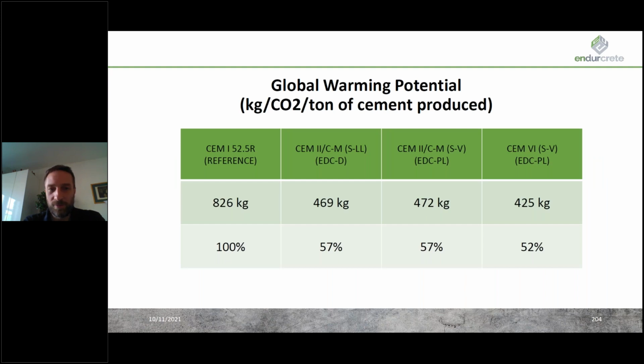So if we compare the global warming potential measured in kilograms of carbon dioxide, which is the most important parameter in this analysis, of the reference cement with the alternative EnDurCrete cements, we can see that we have achieved a very significant reduction. And maybe you remember that in the beginning Arno was presenting that the target of the project was to achieve the 30% reduction, and actually all 3 cements achieved more than 40% reduction of carbon dioxide production. So we can say that this was very successfully achieved.